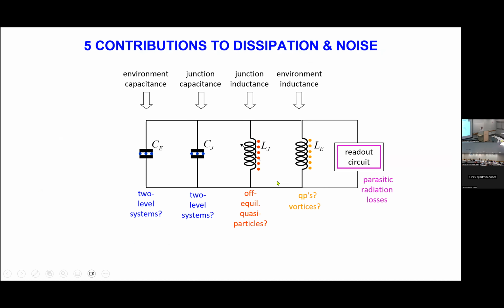Something that is linked to vortices is that you can have broken Cooper pairs. Normally, at 20 millikelvin, if you have a piece made of aluminum, there would not be any broken Cooper pairs. But in practice, we see that some Cooper pairs are broken. There are some free electrons, and so we have to get rid of them. One way to get rid of them is precisely using vortices, but not mobile vortices. You want fixed vortices that will gobble up the broken Cooper pairs.